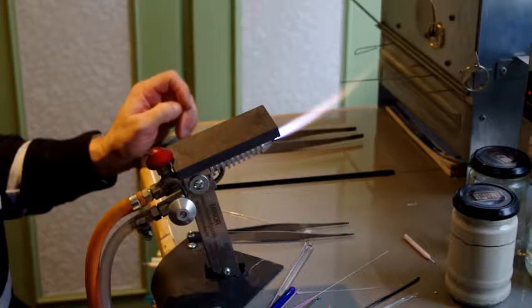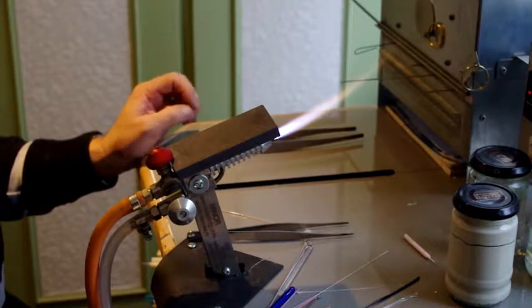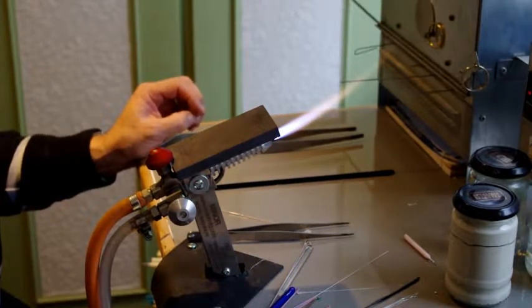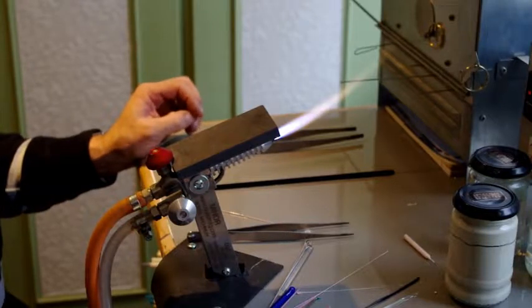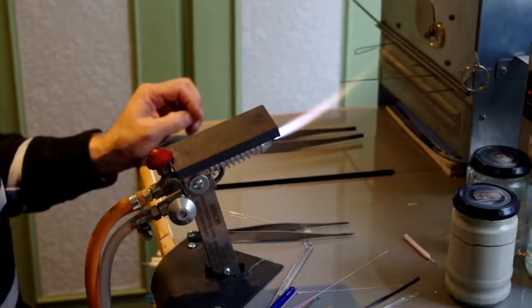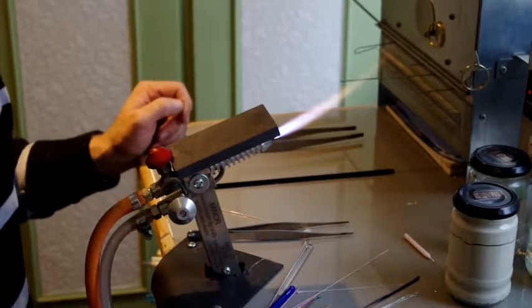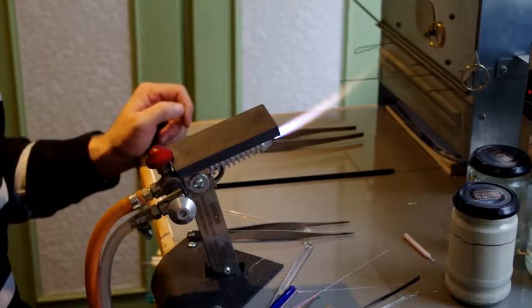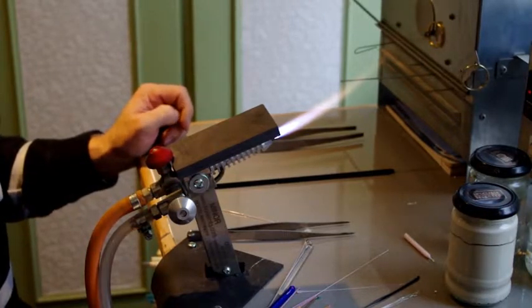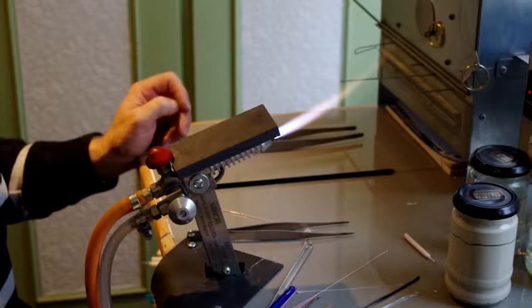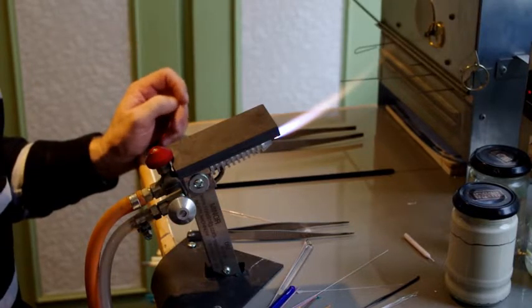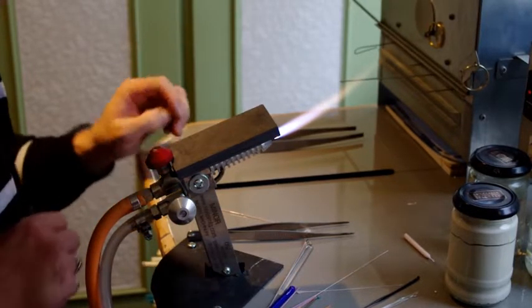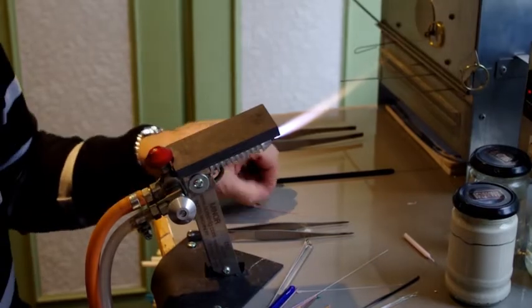it will switch itself off and it will slowly cool down over a period of 2 hours down to room temperature, which means that the beads, when they come out of there, will not crack or break. In fact, they're as hard as marbles and you can actually throw them onto concrete and they will not smash. Very hard. Right.